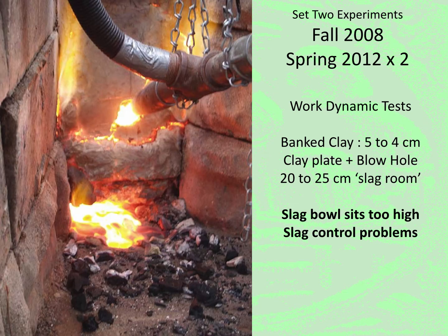In each of the smelts in this set, it was found that the air did not properly penetrate to the interior of the furnace. This in turn caused the slag bowls to all form too high and too close to the front of the furnace. This would then result in the requirement for a lot of intervention in the control of slag. Eventually, each of these furnaces had to be tapped.